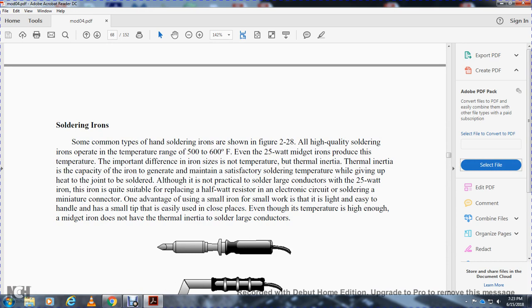The high quality soldering iron operates in the temperature range from 500 to 600 degrees Fahrenheit. Even the 25 watt midget irons produce this temperature. The important difference for the iron size is not temperature but thermal capacity. Thermal capacity is the capacity of the iron to generate and maintain satisfactory soldering temperature while giving up heat to the joint to be soldered. Although it is not practical to solder large conductors with a 25 watt iron, the iron is quite suitable for replacing a half watt resistor in an electronic circuit or soldering at a miniature connector.